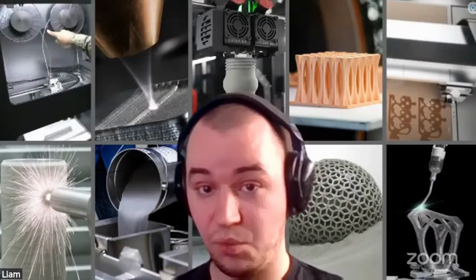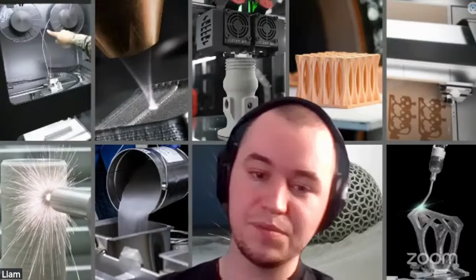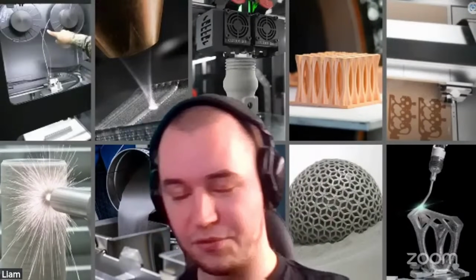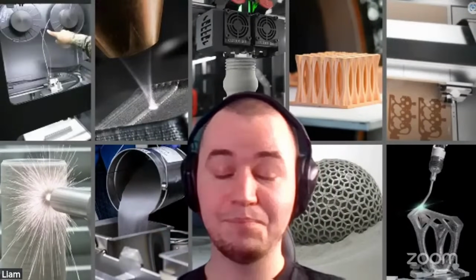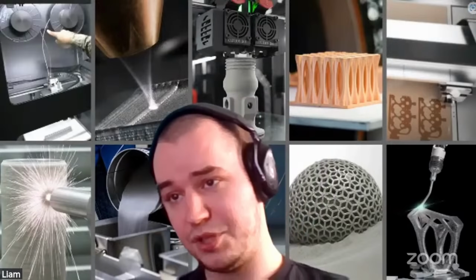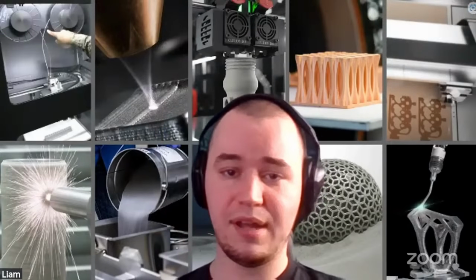Yeah, you can print with aluminum, but again, it has to be processed and kept oxygen free to get good results. And to be clear, when you buy the material that is ready for 3D printing, generally it's in a sealed container that is already oxygen free, because as soon as you open it, it's exposed to oxygen, and now you're going to have oxide layers around all those particles, which is going to reduce the mechanical performance of your print. And then you put it in the machine, and the machine flushes it with argon, and so you're good to start printing.